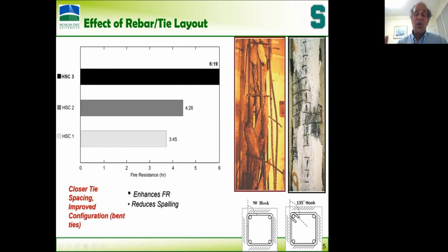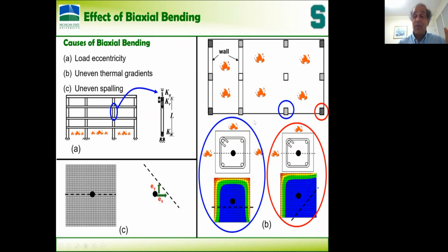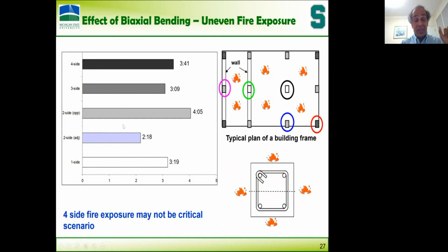Then when a column, for example, is subjected to concentric loading under fire, you have episodal spalling happening on different sides. So that means your concentrically loaded column becomes eccentrically loaded, due to development of thermal gradients when only one side, two sides, or three sides are exposed to fire. So a three-side exposure, or two adjacent sides exposed to fire, can give much lower fire resistance than a four-side exposure. This can cause significant problems in real life. Okay, so let me skip this.